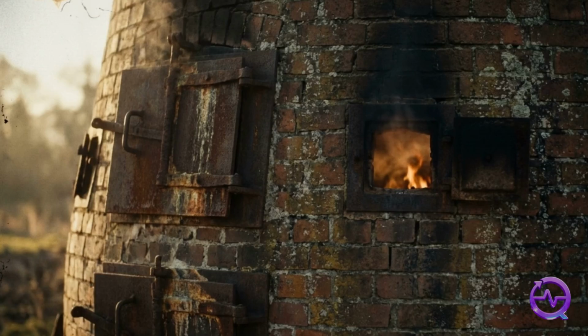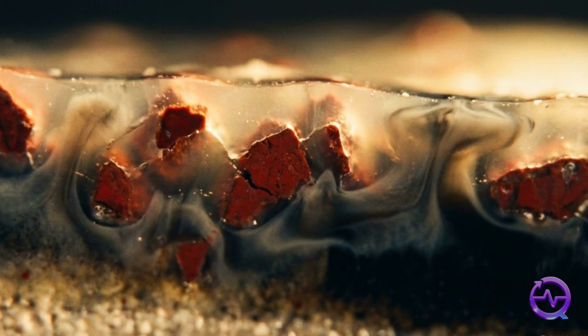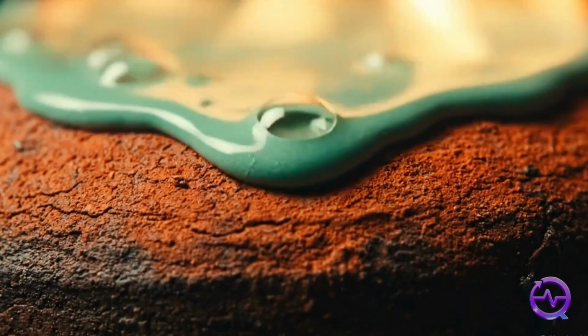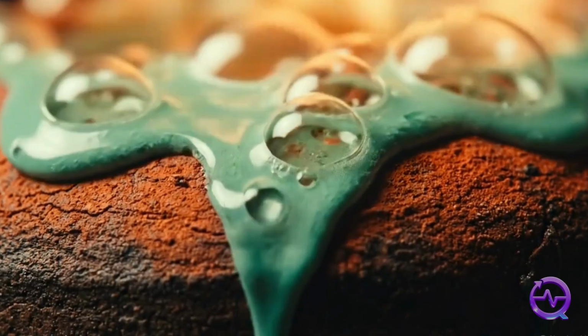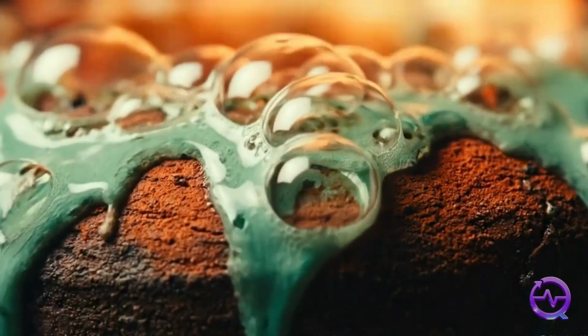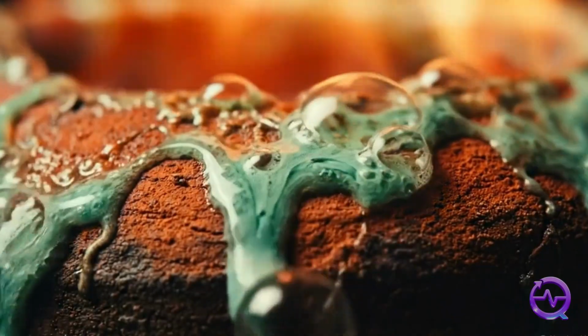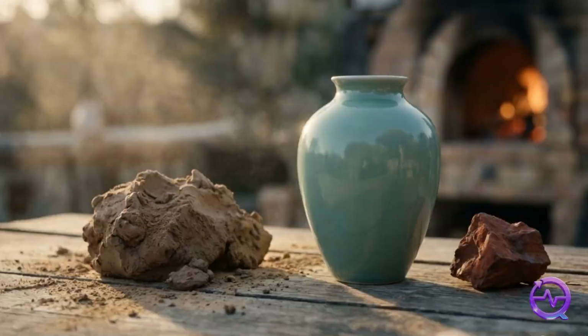In reduction firing, the kiln is intentionally starved of oxygen at its hottest moment. This oxygen starvation forces the fire to strip oxygen atoms directly out of the glaze's metal oxides. When the fire removes oxygen from red iron oxide, the chemical transition produces the iconic seafoam greens of traditional Celadon. This mastery over chemical and atmospheric reactions allowed humans to permanently bind liquid glass to solid earth.